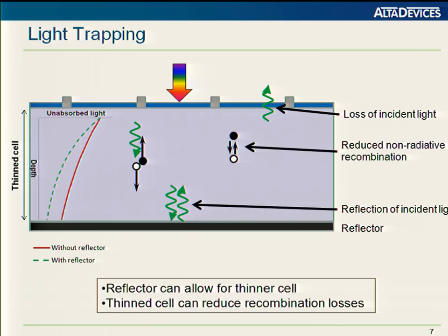So again, using these green photons to represent light from the sun, most of it's coming in normal and reflected normal off the back surface. So straight away we get two passes effectively through the material. Again, I draw unabsorbed light as a function of depth into the cell. And with the reflector shown in green, the dashed green line, we can make the cell not quite twice as thin, but significantly thinner than you'd need to make a cell without the reflector on the back.